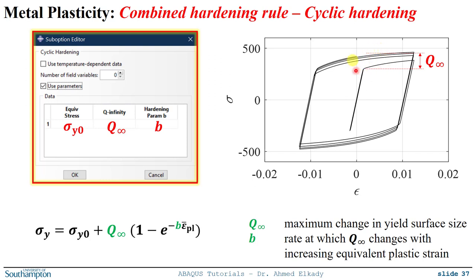What is the rate? So if you look at this example plot over here, you see that in the first cycle you increased maybe 60 megapascal, and then in the subsequent cycle you increased by only 10, and then the one after you increased by just 5. So this rate, how you saturate to the maximum value, this is the parameter B, which is the rate. So again, ABAQUS is going to use these values Q and B in this equation to find the size of the yield surface at any increment during the analysis.